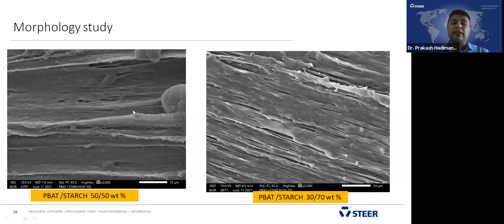The morphology study we observed at 50-50 and also 30-70, 70% starch. In the 50-50, the morphology shows the complete homogeneous dispersion of this PBAT. You observe there is a layer, this layer shows the PBAT layer. There are small dots in between. You can observe these are starch powder.